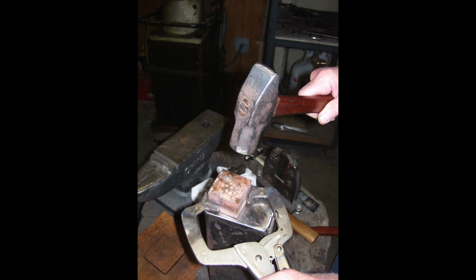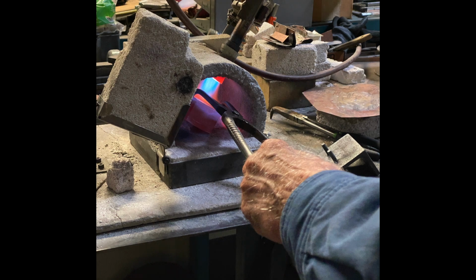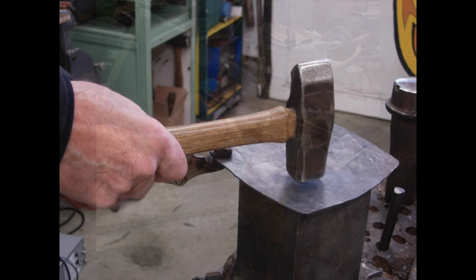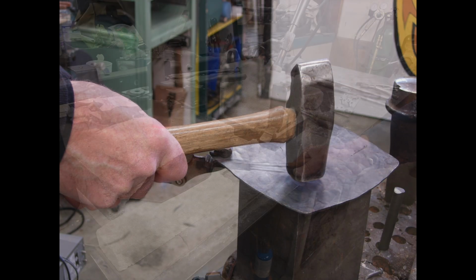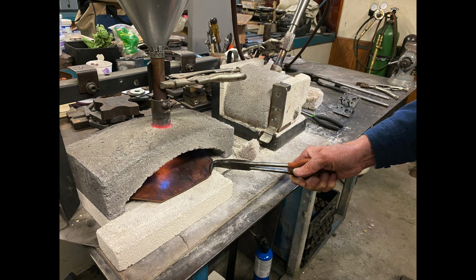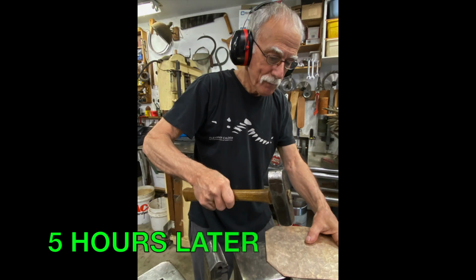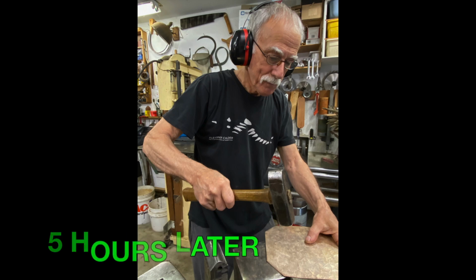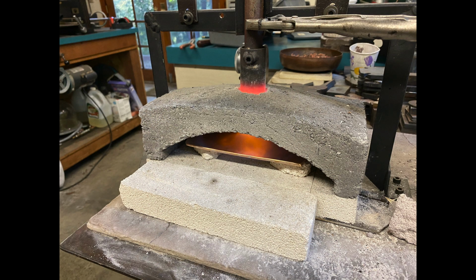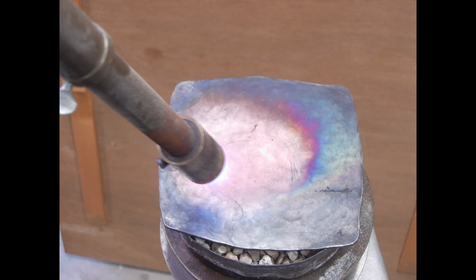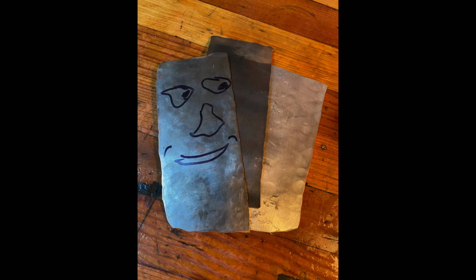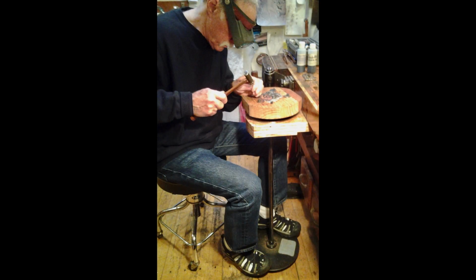After each round of careful forging, the billet is annealed. This forging and annealing process is repeated many times. Annealing can be done in an easily built oven or with a torch. It truly takes hours to forge this billet into a finished sheet for patterning. You see some here. I want to show you how this pattern works by using layers of clay.